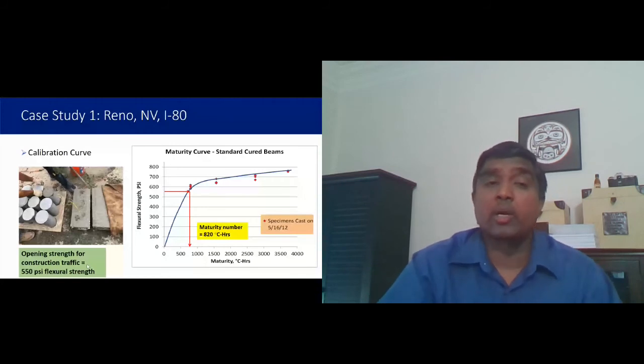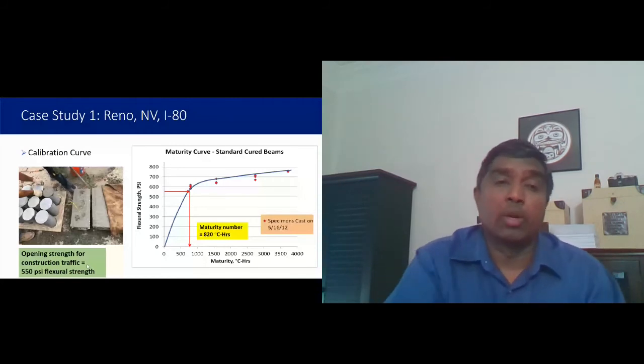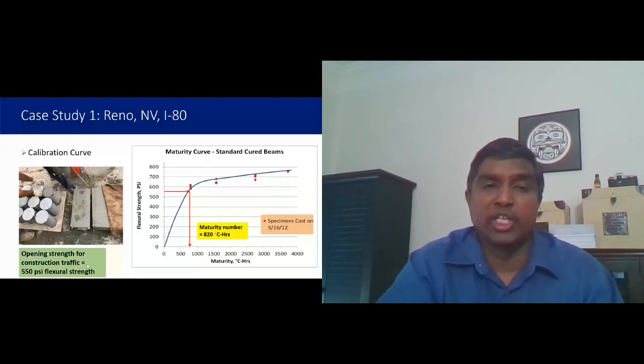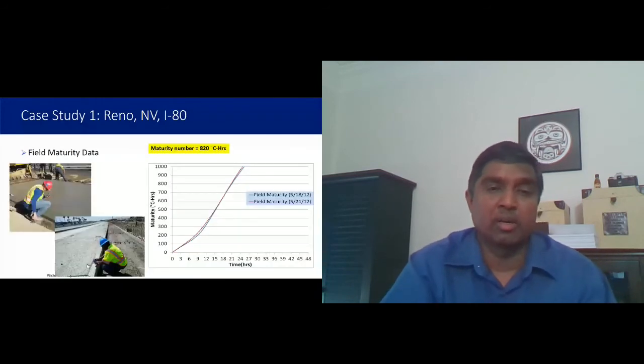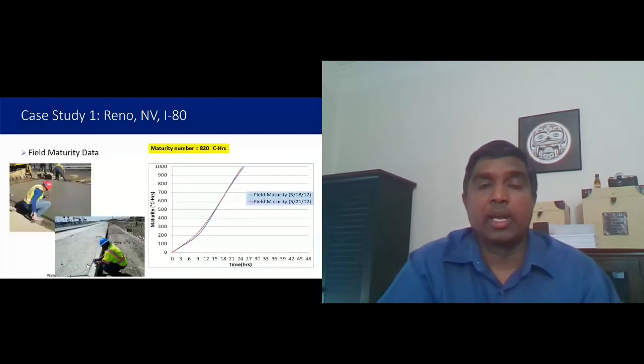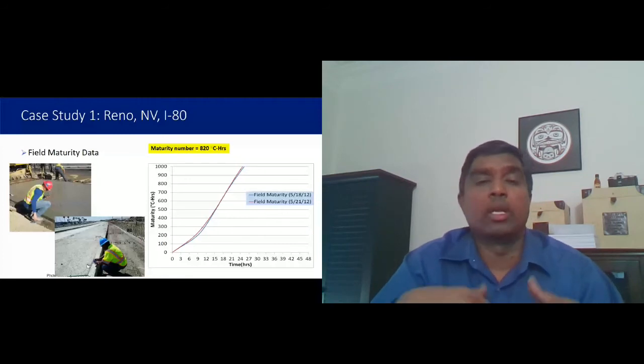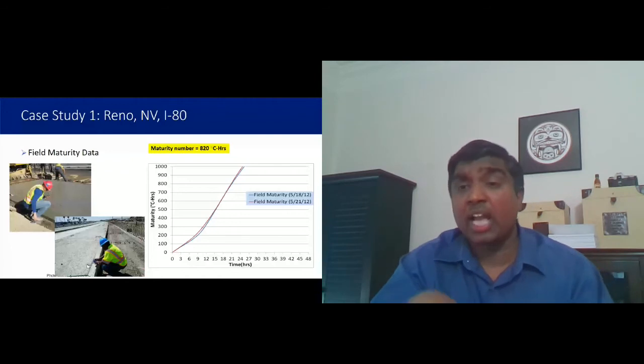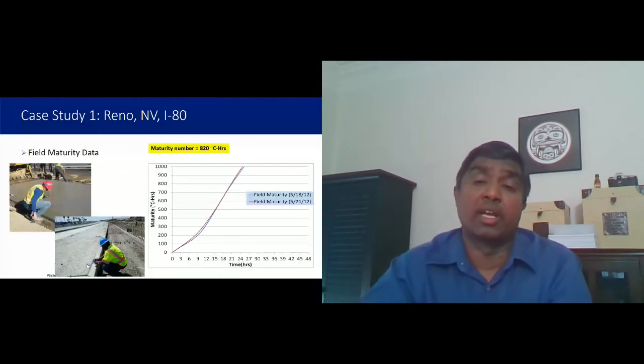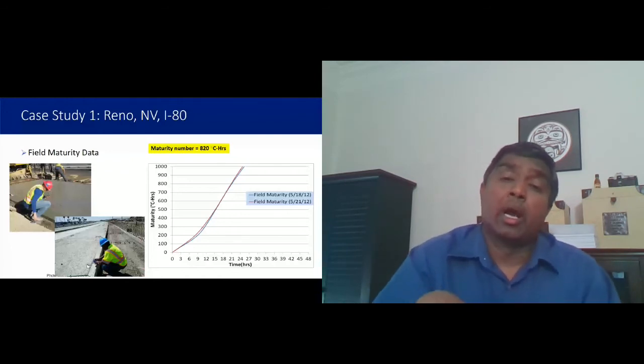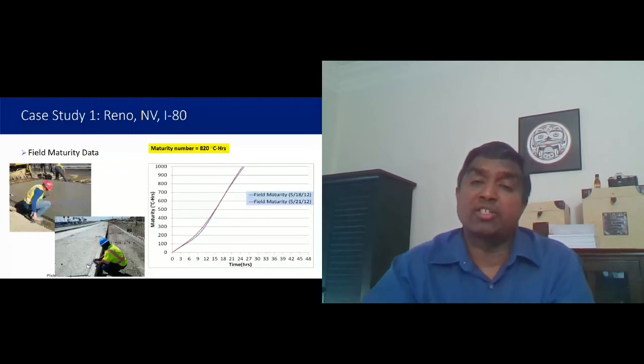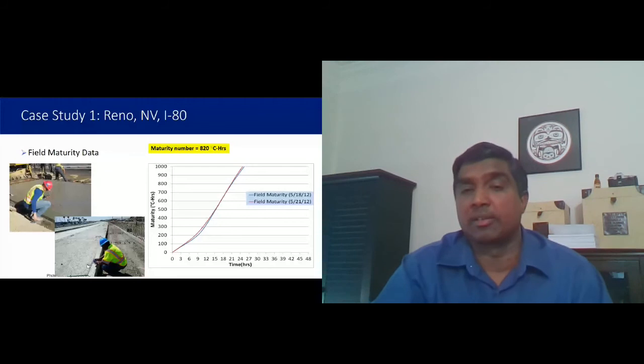So then what we did was we went to the field and we requested the contractor to instrument a sensor in there, which she did. And then a few days later, we went and downloaded the data. And we actually put 2 different sensors on 2 different days. And as you could see, for the days when we put these sensors, the maturity numbers were almost identical.